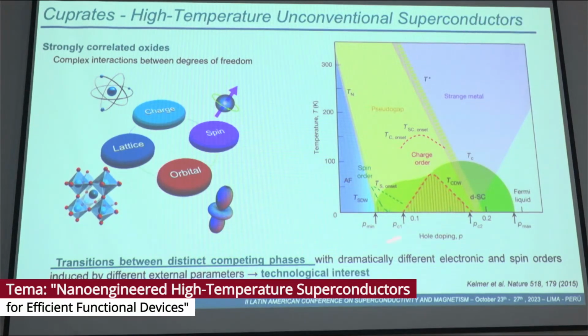In the case of YBCO or high TC, we have a complex phase diagram where we have the superconducting state below a dome, which is controlled by the critical temperature, and here the doping of the material would change a lot the properties of the material, going from an antiferromagnetic state to the normal state, and in between a lot of different quantum phases that can be used for different functional applications.